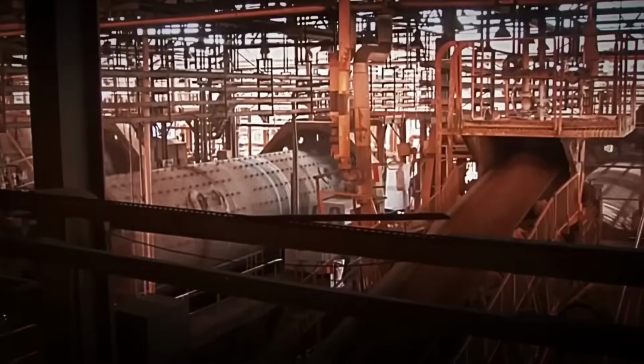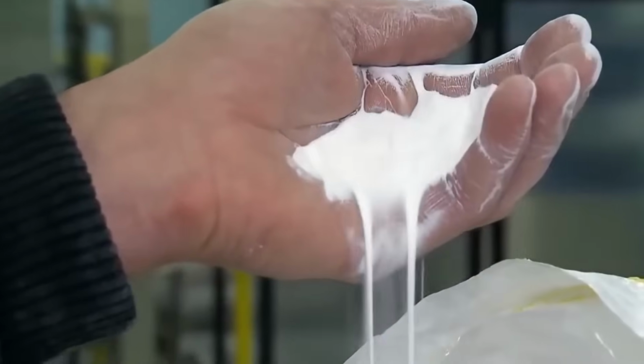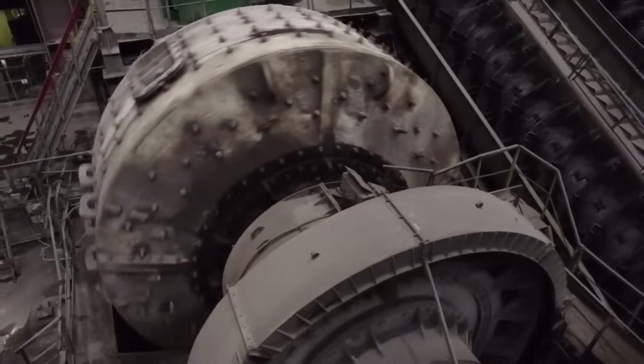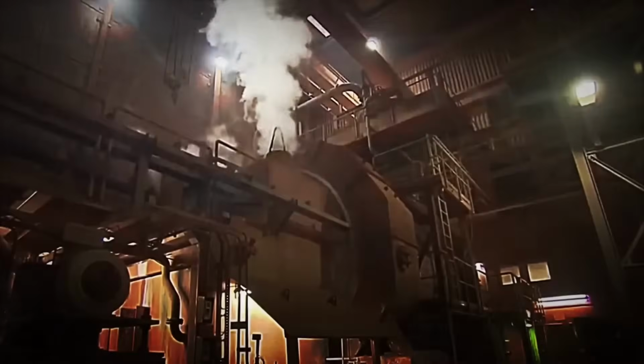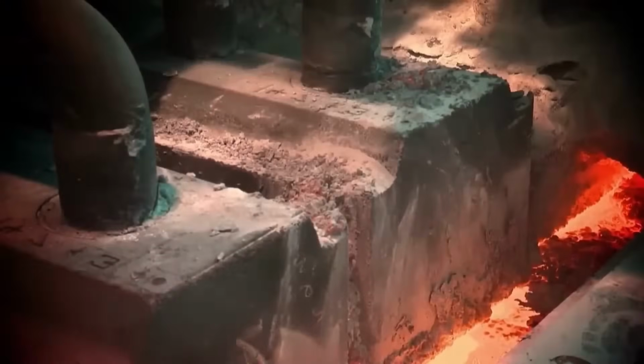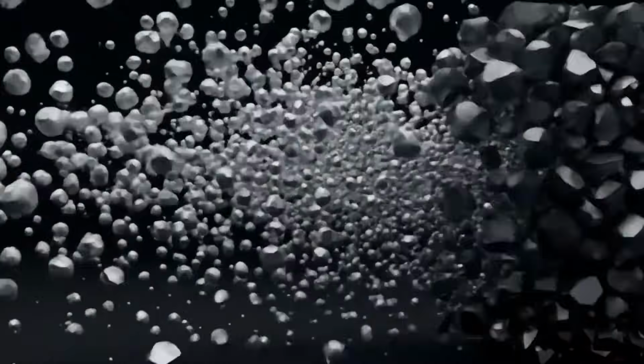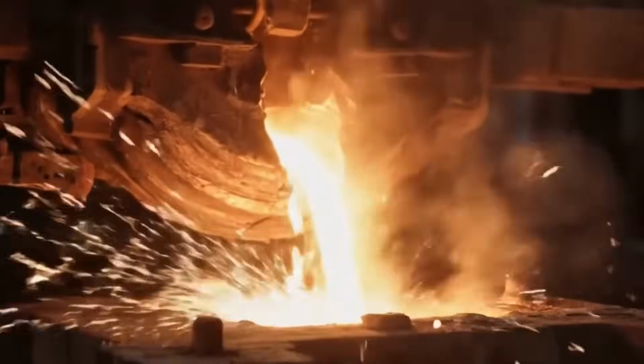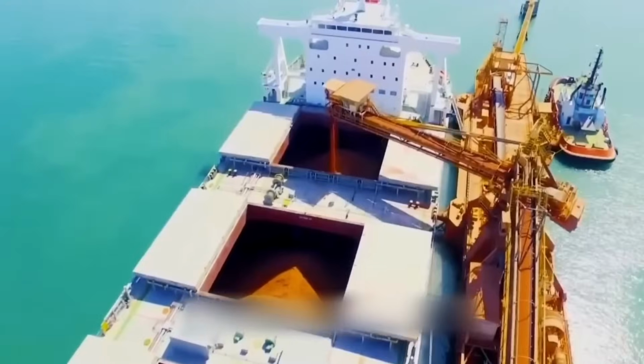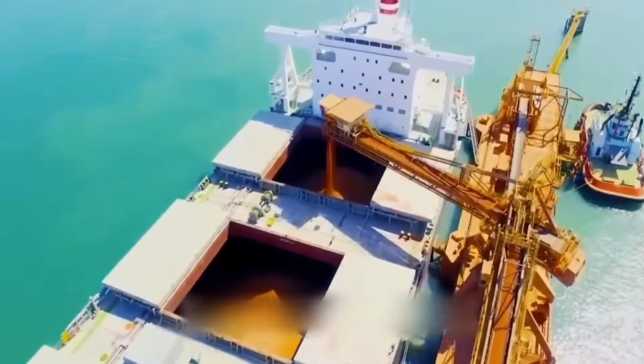The valuable part is the dissolved aluminum oxide in the liquid, but first the leftovers need to be removed. The mixture is filtered, separating out the solid impurities. These impurities, mostly iron-rich and known as red mud, pile up fast. For every ton of alumina produced, the industry generates about 2 tons of this red mud, highlighting just how much waste comes with refining bauxite.